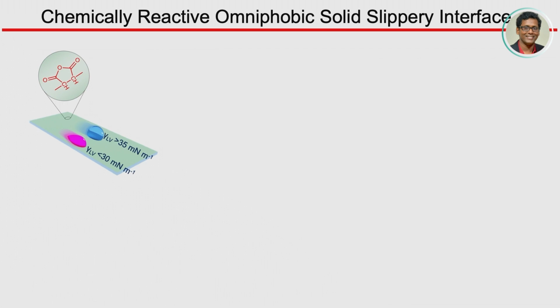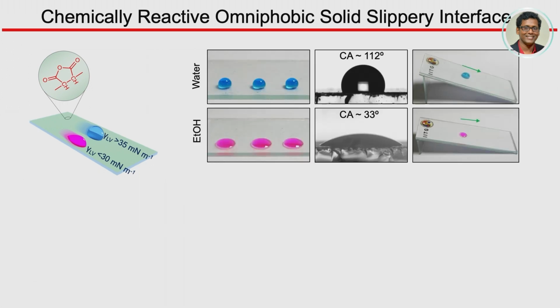As you can see here, these are two examples where we took water, whose surface tension is way more than 35, around 72 millinewton per meter, and ethanol, which is way lower than 30, right? If you put them, you can see the contact angles are not really that extremely repellent, right? But when you tilt them, you can see they nicely slide off, leaving behind no trace of either water or ethanol.